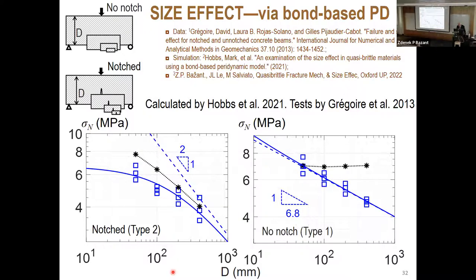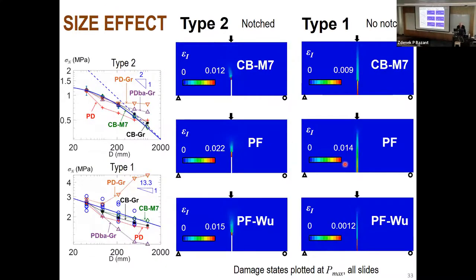Now, we did not do any calculations. We took the data from his paper, placed them here in log-log plot, and you see beautifully agrees with the size effect curve, also type 1. The slope is, of course, much less. And then here, 1 over 2, 1 over 6.8. And we plot here. All right, and his data are deviating. Here, not so much. These are Hobbs data. Hobbs analysis. And it was bond-based peridynamics. This is the original one. And here gets no effect at all. So this cannot be, of course, statistical. That simply doesn't work. Now, what is also important is to look at the picture of damage. I will show damage plots only for the maximum load states.